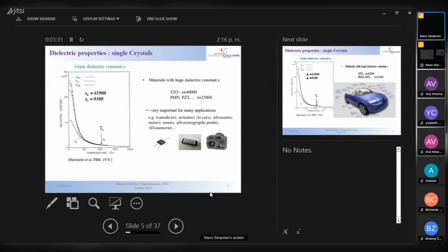Another property, which will be the property we discuss today, is the dielectric constant, or the dielectric permittivity. As you see here, that's the temperature on the abscissa, and when you lower the temperature, the permittivity increases, and in strontium titanate, it can reach a value up to 40,000, which is huge for a material. As a reference, usually materials have a permittivity of 10 or 100, but to have more is not common. So this material has a huge dielectric constant, as well as the complex ferroelectric materials, PMN, PZT, which exhibit a permittivity of over 25,000, which is also very huge.